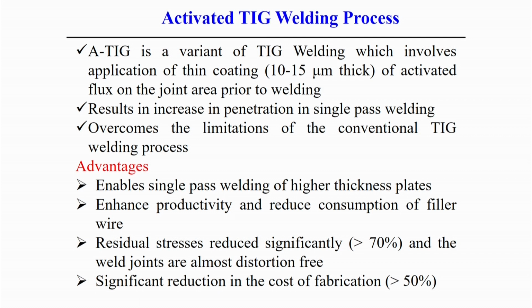So, what are the typical advantages of this process? The basic advantage is that it enables single pass welding of higher thickness plates, and it is not necessary to do multiple welding passes, because it considerably increases the depth of penetration. So, multiple passes are not required in this case. That is one significant advantage of this process. And of course, it enhances the productivity and reduces the consumption of the filler material. In this case, residual stress can be reduced significantly, by more than 70%, and the weld joints are almost distortion free.